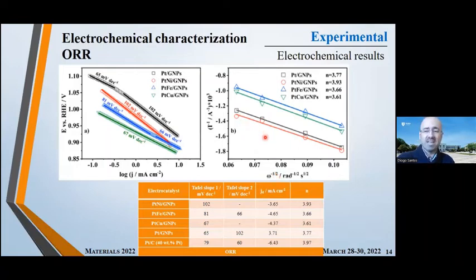Based on this plot and using the Koutecký-Levich equation, we are able to calculate the number of exchanged electrons during oxygen reduction, which was close to 4 for the four materials. So the four materials behaved very well, had very good performance for the oxygen reduction reaction.